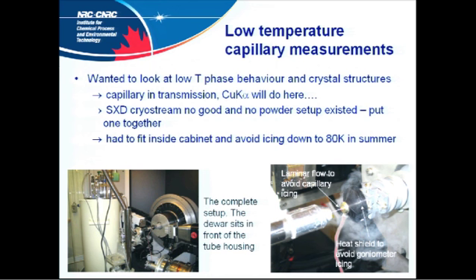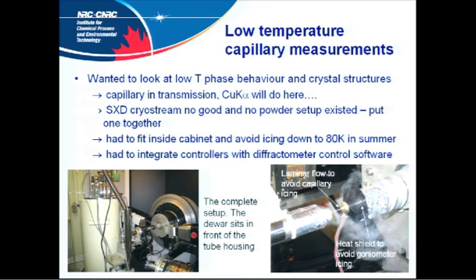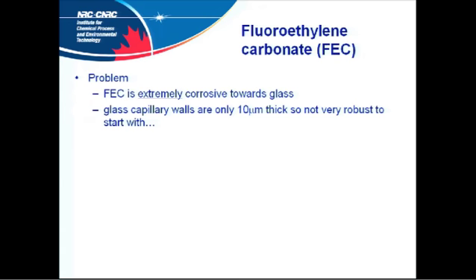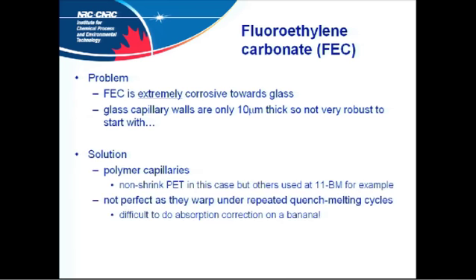And you actually want to avoid icing during the summer. So you also have to integrate the controllers with the diffractometer to be able to do a complete ramp soak. The other sample problem is very corrosive, therefore glass capillary is not a good idea. Polymer capillaries. Now, this is often used at synchrotrons. Here, not quite as perfect because you're doing repeat quench and heating, so they end up like a banana. The vacuum that you start pulling will start distorting the polymer capillary.